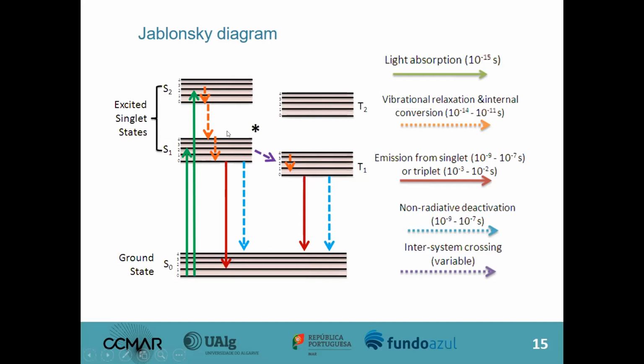There is also a note I want to make here. The excited state can also react, and if the molecule reacts, it doesn't lead to any fluorescence. Or it can be quenched by other compounds that are nearby, namely oxygen. So oxygen has a strong influence on fluorescence behavior. It decreases the emission intensity.